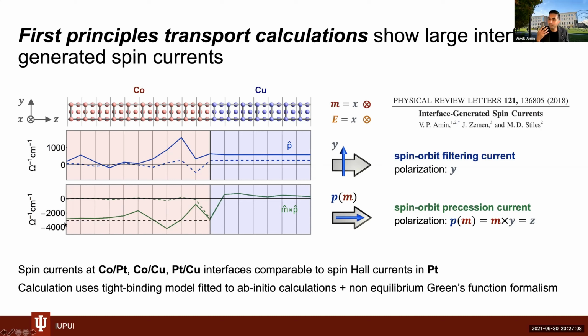So there is some bulk spin current that is also occurring in cobalt. But if I turn off spin-orbit coupling in cobalt, I get dephasing to 0, meaning that spin current is essentially killed through incoherent precession. So what's going on here? That tells us that there is a spin current that is also generated in the cobalt layer, in the ferromagnetic layer, that arises from spin-orbit coupling, which can essentially compete with the interface-generated current as well.